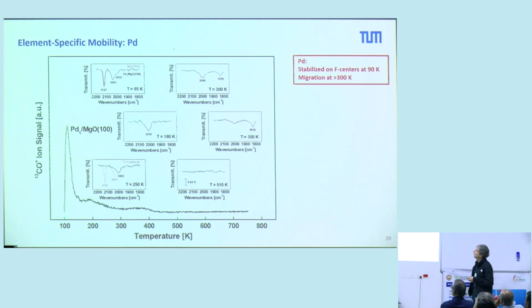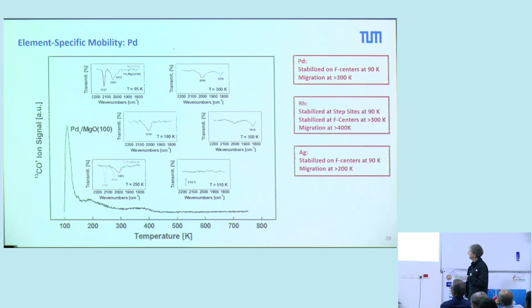And then if you go to larger temperatures, above 300 K, you suddenly observe a bridge-bonded CO. That means you have to have two palladium atoms in the neighborhood so that you have a bridge-bonded CO. That means at this temperature, they will diffuse. And of course, if you heat up, you produce larger clusters. So the dynamics is extremely important if you talk about single atom catalysis, because you have to know what you have on the surface. We did similar experiments on rhodium and silver.